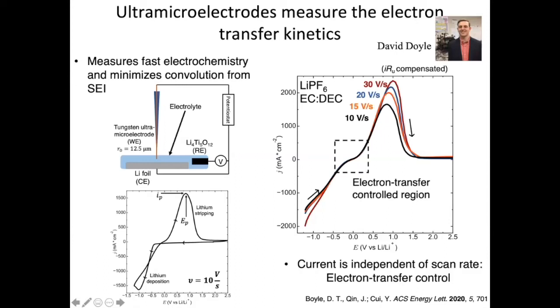And then when you are doing the CV measurements, scan your voltage, measure your current, you can scan very fast. With this microelectrode, the cross-section is so small, and the lithium flux going in is towards this kind of point source, right, point source. And it's less limited by the mass diffusion. So through this voltage curve, the CV scan, you can see J, that's current density versus the voltage. You can scan very fast, up to 20, 30 volt per second. So you're finishing this measurement, one scan, in less than a second.